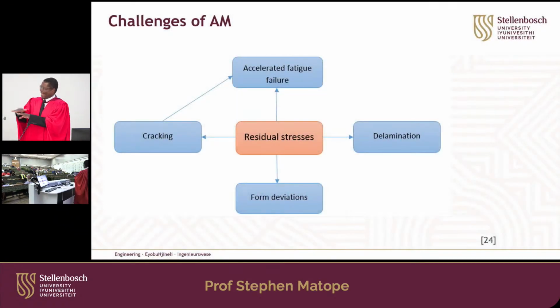Because you're melting your powder, adding another layer, melting it, adding another, right? So there are thermal changes which can really result in residual stresses, which can result in delamination, the layers not really merging or fusing together. Then also different deviations, some distortions, instead of coming up with the right thing, you find it maybe warped, and the like. Also cracks because of these thermal stresses. And also fatigue again.